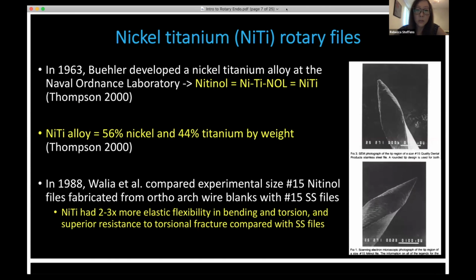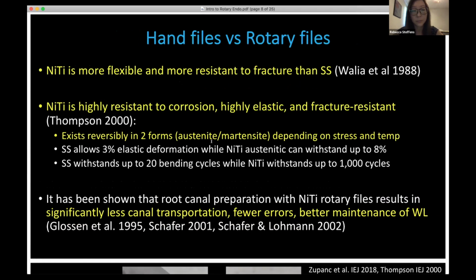This conversation started in 1988, when Walia had a study that compared experimental size 15 NiTi files that were fabricated from ortho arch wire blanks with a 15 stainless steel hand file. These are depicted on the right. Through these tests, they ran 3 different tests of the materials in the files and found that the nickel titanium had 2 to 3 times more elastic flexibility in bending and torsion and superior resistance to torsional fracture compared with stainless steel. That's what started this conversation with nickel titanium.